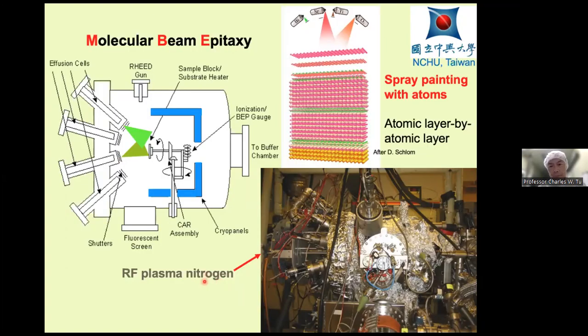Here, you may see why we wrap a $1 million machine with aluminum foil, like a baked potato. This is to achieve ultra high vacuum. Because normally, when we pump a system, it will be limited to about 10 to the minus 8 torr. That is because there are always some molecules, especially water molecules, which will be adsorbed on surfaces, and then they will desorb and adsorb again. So the pumping is not very efficient at such a high vacuum.